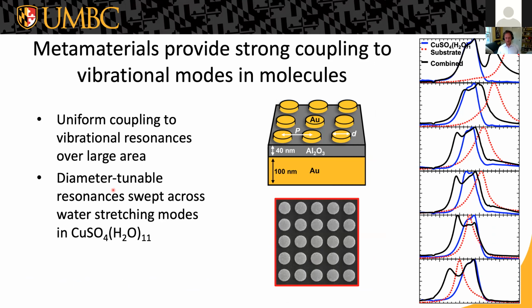The last thing I'm going to mention here is work with Matthew Sheldon at Texas A&M, where they've made a sort of metamaterial, something very similar to the particle on a metal film that we looked at before, but now with an array of these particles coupled together laterally in a collective resonance that provides highly uniform fields, so that if you put down a material, in this case hydrated copper sulfate, and coat this metamaterial with that molecular material, then you can get coupling across the entire thing.